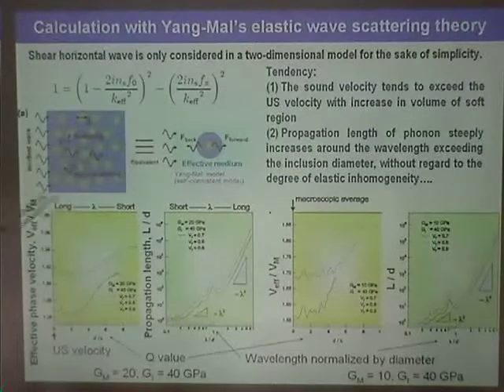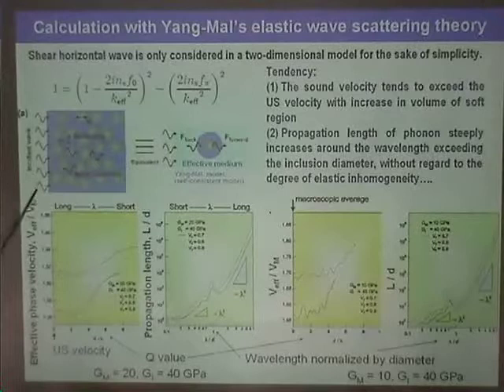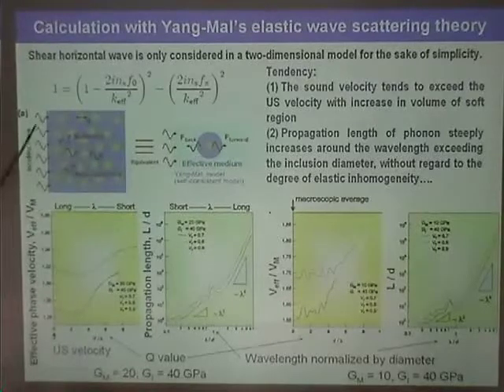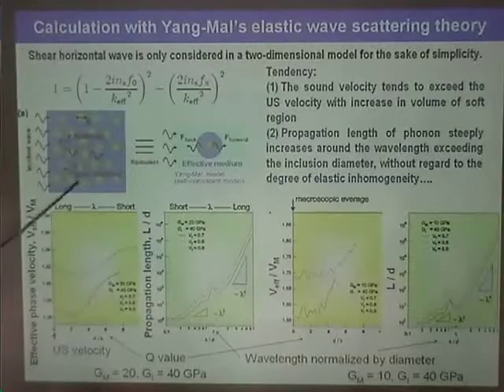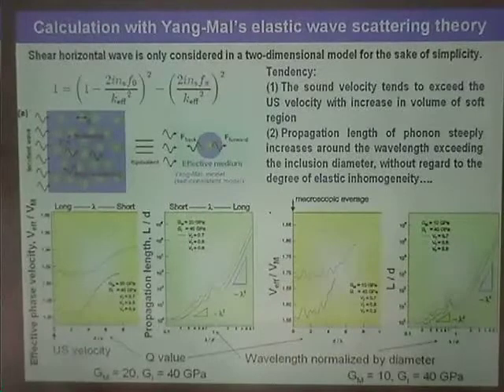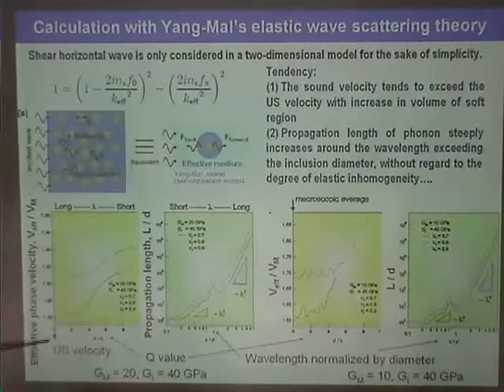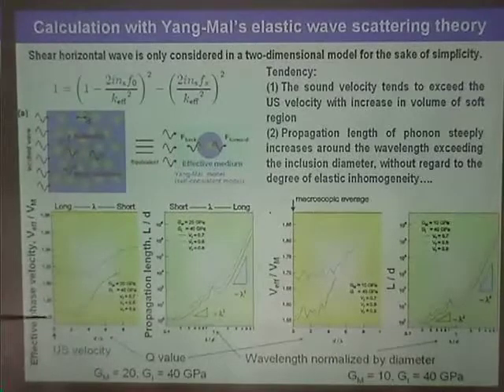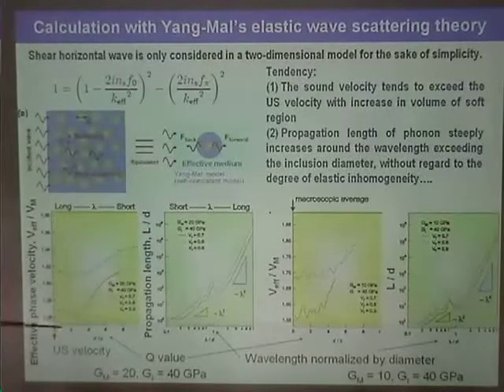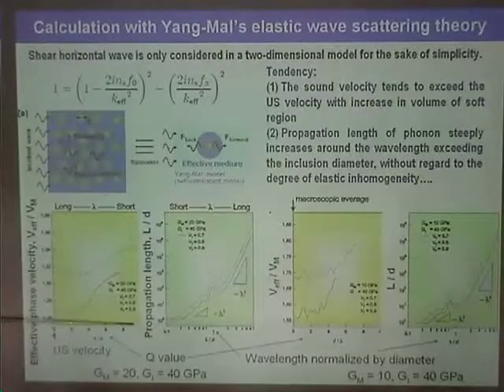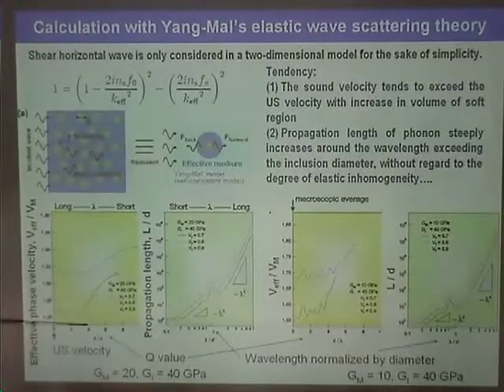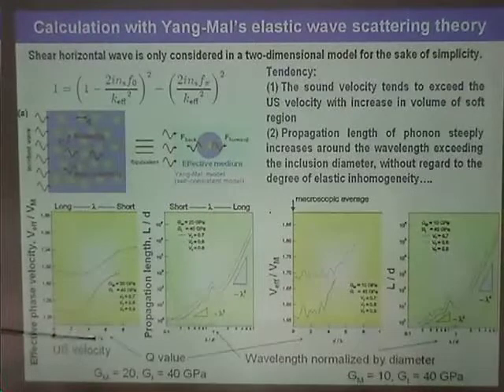To explain this phenomenon of propagation length, we have assuming this model. This blue region is the softer region, and this is the hard region. And the scattering theory is applied. So this is the ultrasonic velocity, and this is the effective macroscopic phase velocity, and this is the diameter. I'm sorry, this corresponds to the Q value.